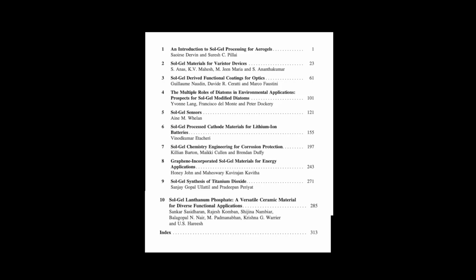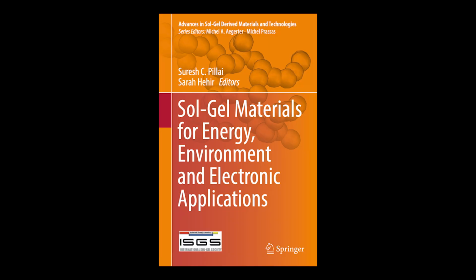Critically, for most of these applications, the anatase phase is superior. For photocatalysis, the crystalline phase is the function. It determines how well it works. Anatase is widely recognized as being far more photocatalytically active than the rutile phase. There are a couple of reasons for this.